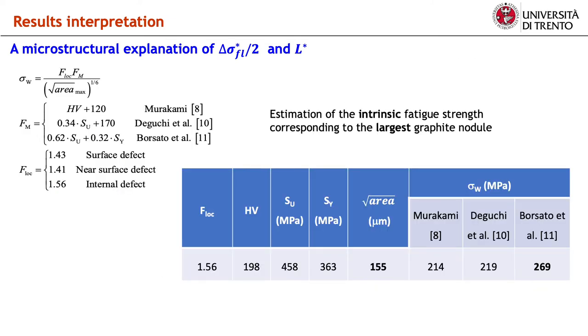Then we tried to predict the fatigue strength of the material encompassed within the control volume using the following square root area models proposed in the literature and successfully applied to DCI. It can be noted that the values of the predicted fatigue strength are significantly higher than the plain fatigue strength experimentally observed, as a result of the different size of the defect triggering the fatigue damage. The value predicted by Borsato is identical to that of the intrinsic plain fatigue strength estimated through the double notch inversion method, thus confirming the suitability of this approach to predict the notch fatigue strength of DCI.